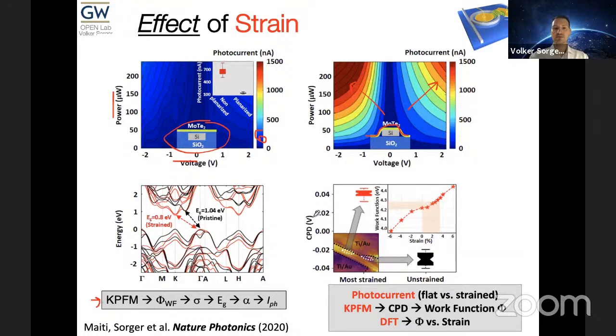This allows us to basically map out the work function as a function of strain. And then we can use density functional theory to use the amount of strain, notice a few percent, that's very high, and perform band gap simulations. And we found indeed, when it's not strained, it is 1 eV, meaning it's transparent for our 0.8 eV telecom wavelength. Once we strain it, we lower the band gap dramatically to 0.8 eV.